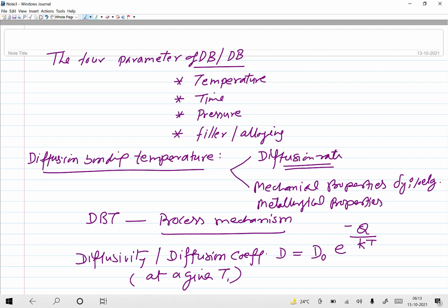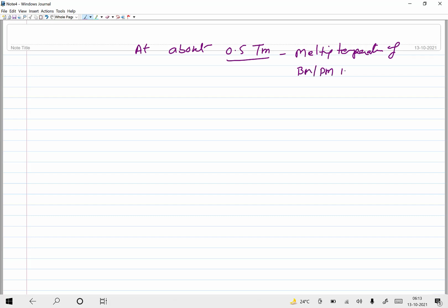The diffusion bonding is usually carried out above the recrystallization temperature, say somewhere at about 0.5 Tm, where Tm is the melting temperature of the base metal or the parent metals in Kelvin. For many metals, the diffusion bonding is also carried out over a wider range of temperature on the higher side, starting from say 0.6 to 0.8 times the melting point temperature in Kelvin.